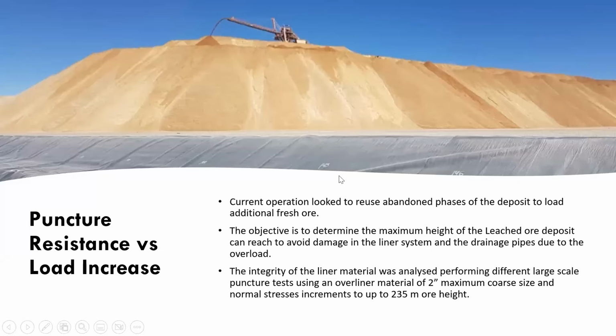In the second study, related to puncture resistance versus a load increase, that was because in parallel, the operation looked to reuse abandoned phases of the deposit to load additional fresh ore. So the objective was to determine the maximum height of the leach ore deposit that can be reached to avoid damage in the liner system and the drainage pipe due to the overload.